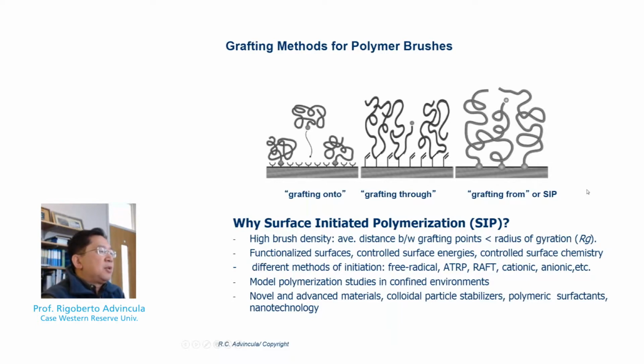or surface-initiated polymerization method. What is surface-initiated polymerization? It represents a grafting, as I mentioned, wherein the grafting point is much less than the radius of gyration. This simply means that an initiator in an addition polymerization method, typically free radical, ATRP, RAFT, cationic, anionic, or metathesis polymerization, originates from the surface. In other words, the initiator is bound on the surface, and the monomer is limited by its diffusion to the surface, and hence it affects the polymerization kinetics dramatically. Now, this can be done on a flat surface, a colloidal particle surface, or other types of interfacial boundaries.